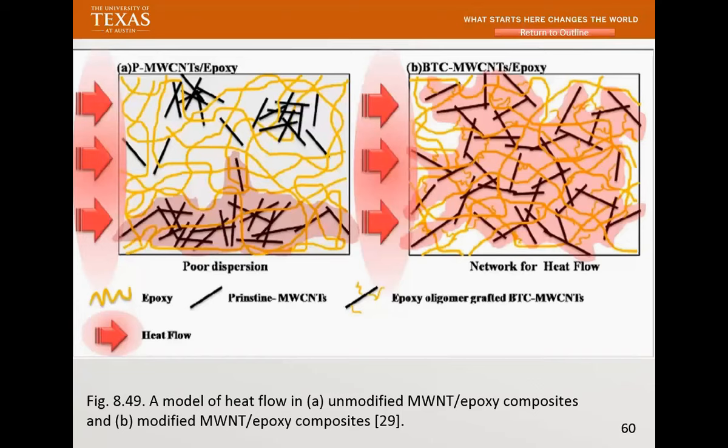So this is a very good network. Okay, but the important thing is you were actually able to connect. If you want electrical connectivity or thermal connectivity, you want them to touch each other, but for mechanical, you want them to separate. So they are competing with each other.